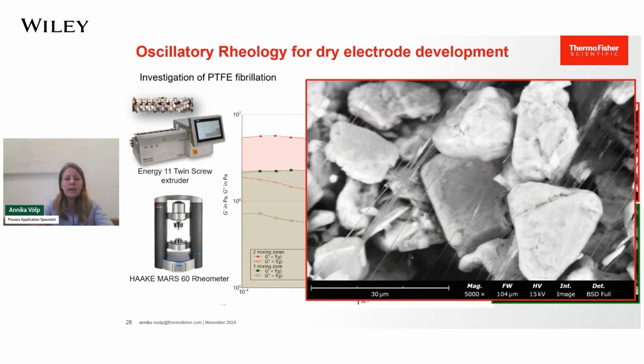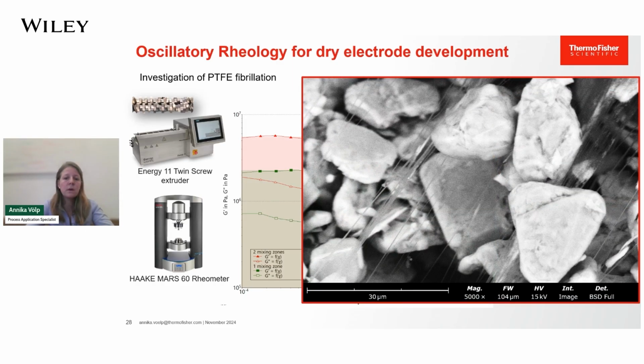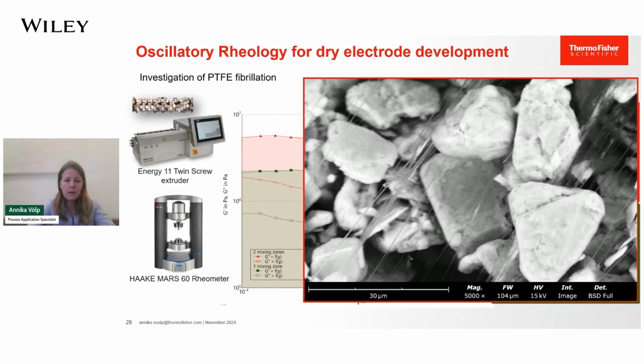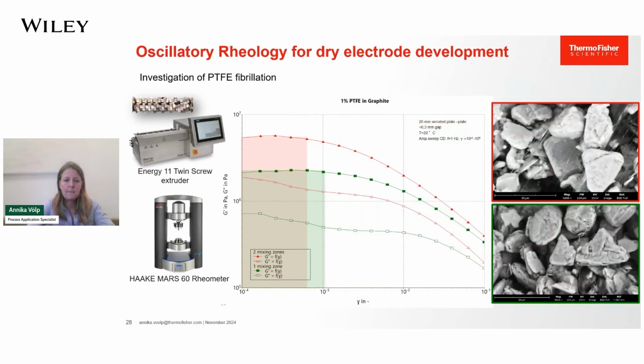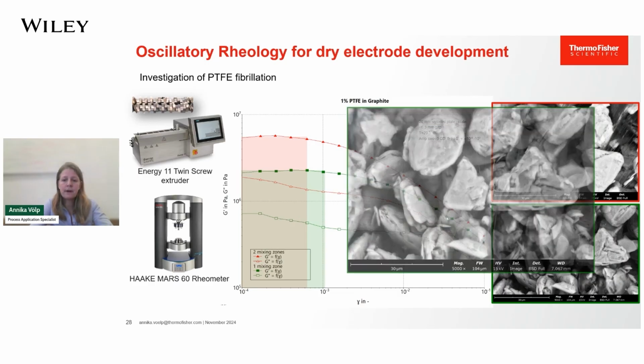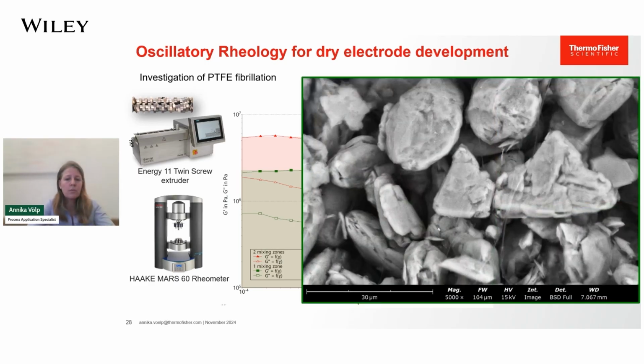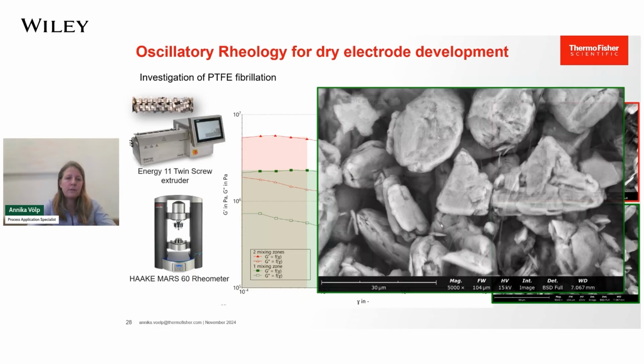The SEM image on the right here emphasizes that by using 2 mixing zones, smaller and more PTFE fibrils evolved, and this reflects then in a stronger network between the graphite particles and a higher G prime, but a gradual breakdown with increasing deformation. The fewer and thicker fibrils in the sample mixed with 1 mixing zone presumably withstand greater deformation, as indicated by the drop of G prime at higher critical deformation.